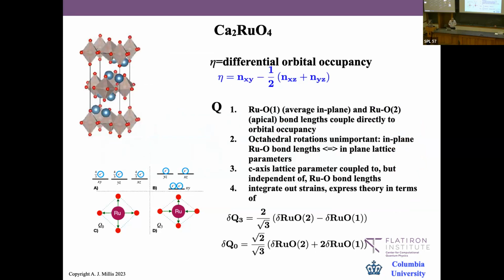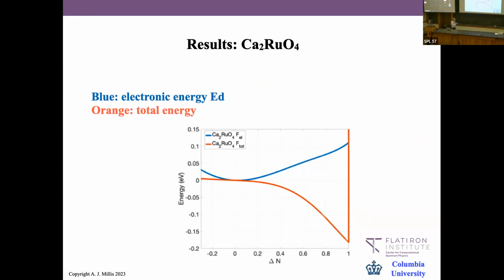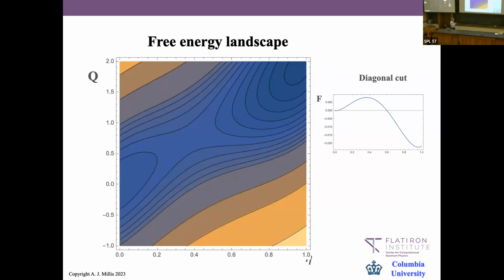Calcium ruthenate, more or less the same story. The electronic order parameter is now capped at 1 because you have 4 electrons, at most 2 can go in here. There's a lattice distortion, you can do the same thing. You see the same story: if you look only at the electronic part, it's minimized at basically 0. The minimum is not exactly 0 because there's no symmetry. If you add the lattice energy, then it goes to as large an electronic disproportionation as it can be. So you can again write a free energy landscape. Here I've represented by contour lines the value of the free energy, and this is a diagonal cut going from here up to here. You see again a metastable minimum at 0,0, a stable minimum here, and nothing anywhere else. So in this material, the transition is driven essentially by an interplay of electronic and lattice degrees of freedom.